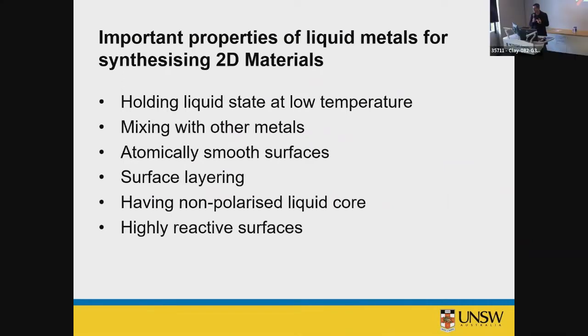Okay, so important properties of the metals which are used for synthesizing 2D materials are this list presented here. They hold liquid state at low temperature. Now, if you remember, when you grow, for instance, on wafer, graphene, you deposit something like copper, then you heat it up at around 1,000 something degrees. Because it melts, almost melts the copper. That temperature is very close to the melting point of copper. So actually, for the synthesis of graphene on a surface of a substrate, you use liquid metal. These are not new. But we're talking about, okay, how we can change the conditions to use post-transition metals with a low melting point for the same purpose.